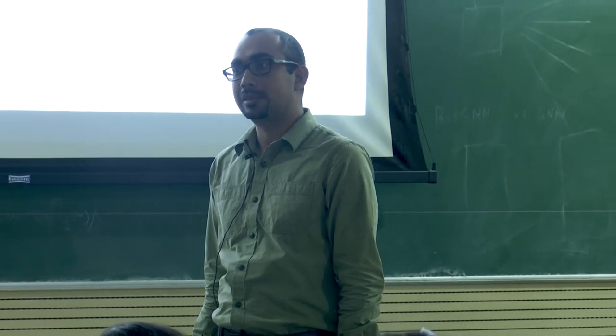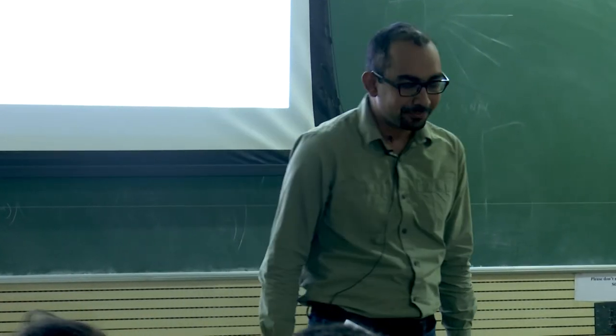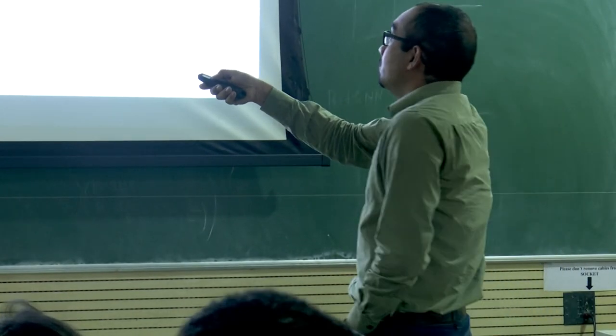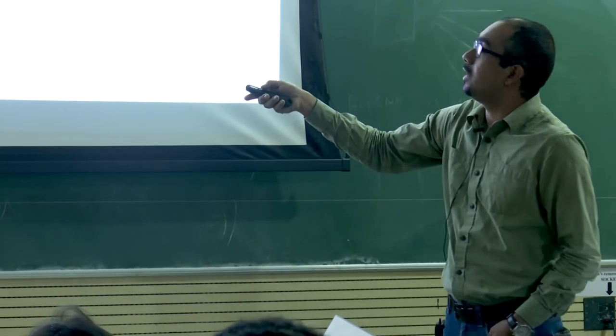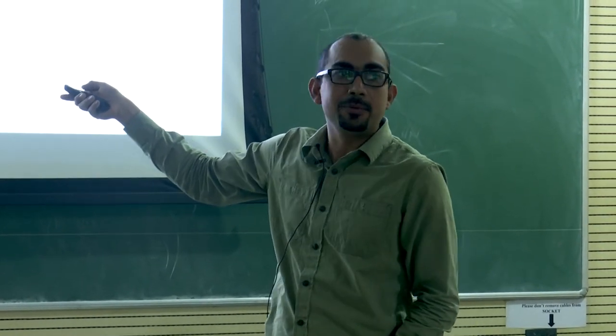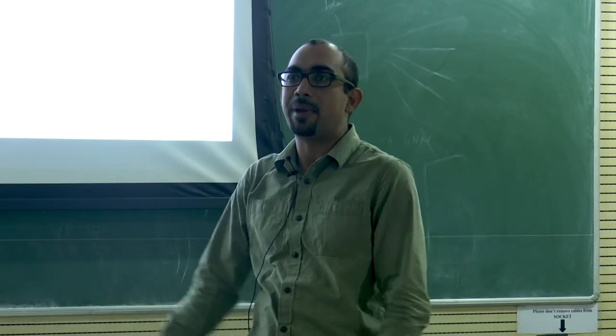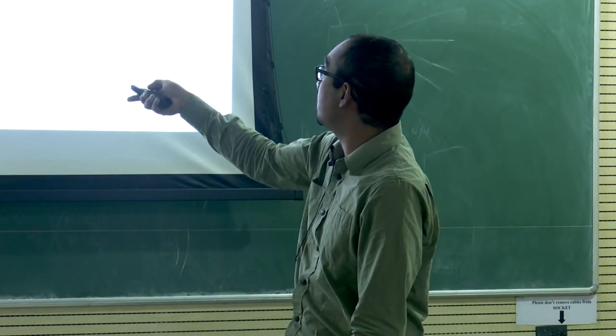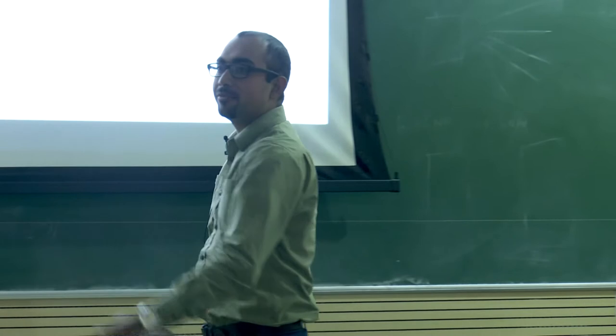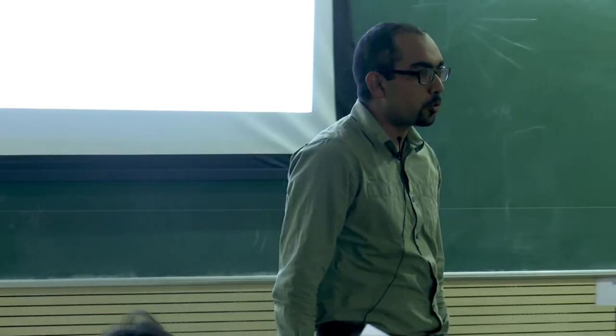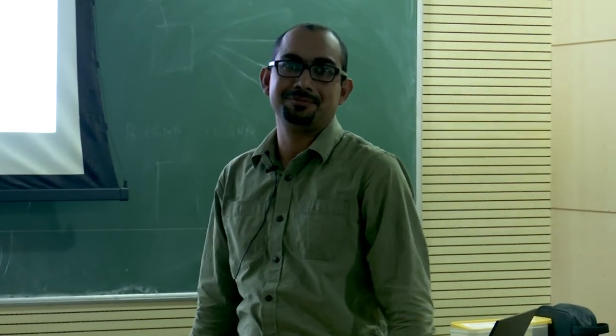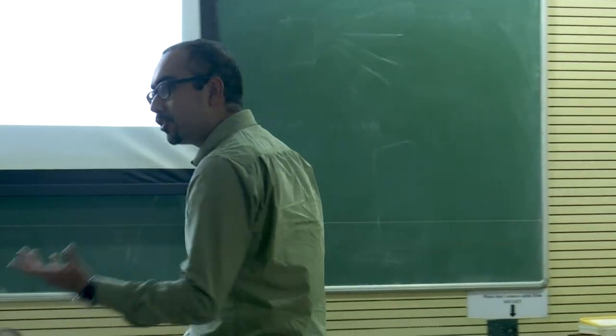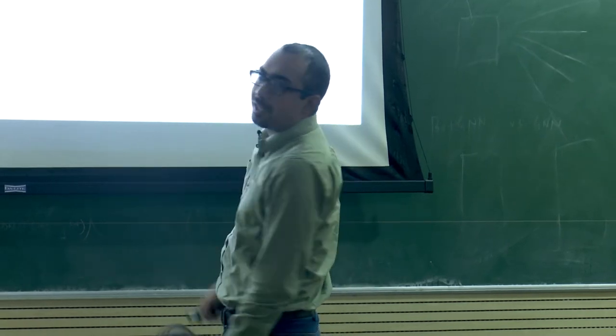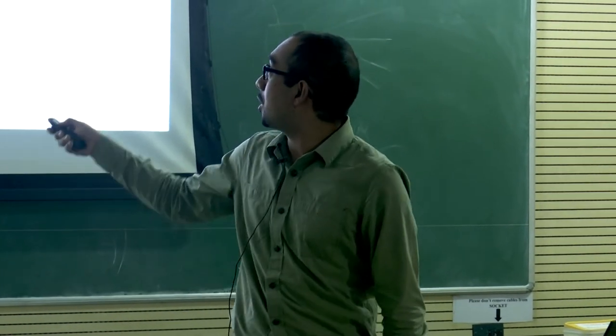What is the problem with superconducting magnets? They quench. So they become normal. Okay, so now let's suppose you put an exciton under a magnetic field. 3 things can happen. First, Zeeman splitting of the exciton. We know that this effect, the bands would shift and split in energy, Zeeman splitting. Then there is Landau level splitting, which Umakant was talking about. This is a pure quantum mechanical effect that the Landau levels are created. I won't go into details when you apply magnetic fields. And you can have diamagnetic shift, these 3 effects. Okay, let's talk about the first 2 of them, because they are interesting for our work.